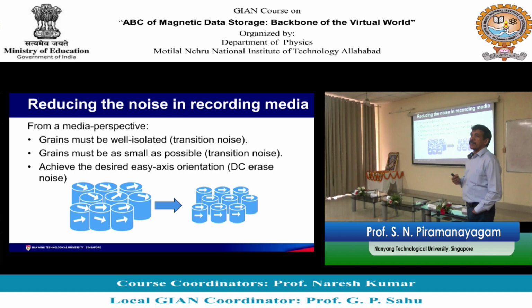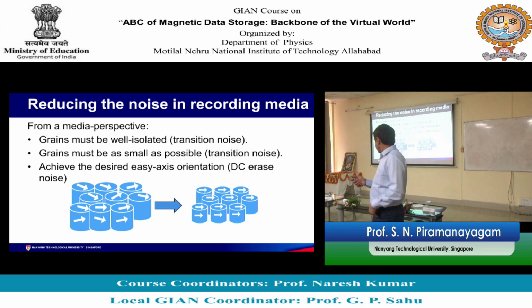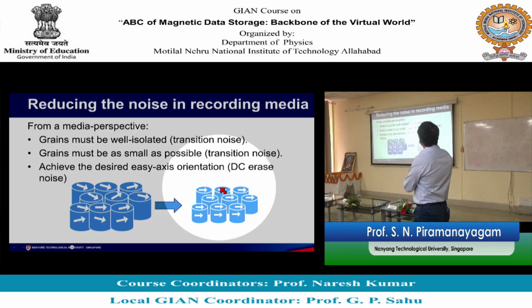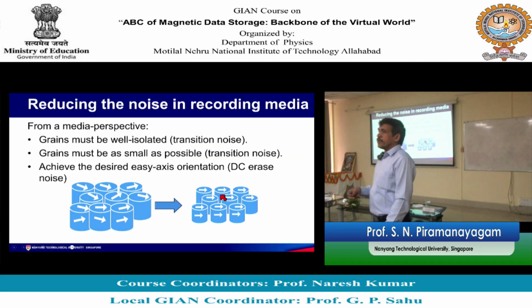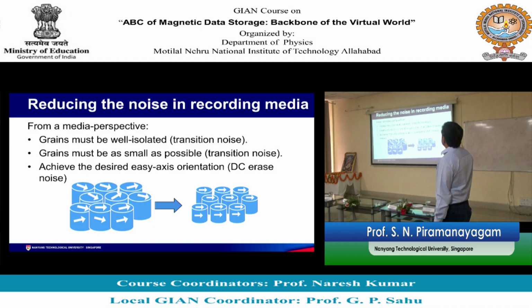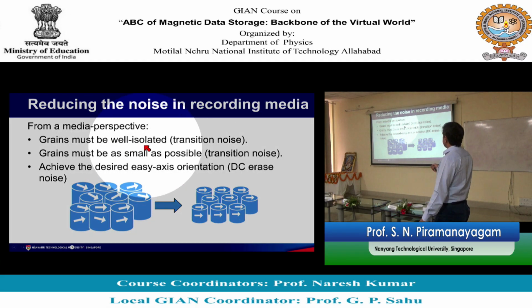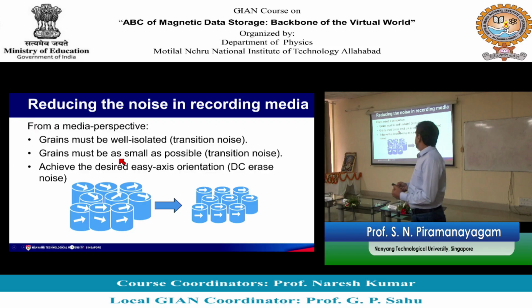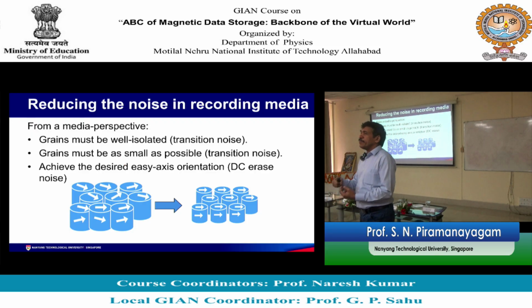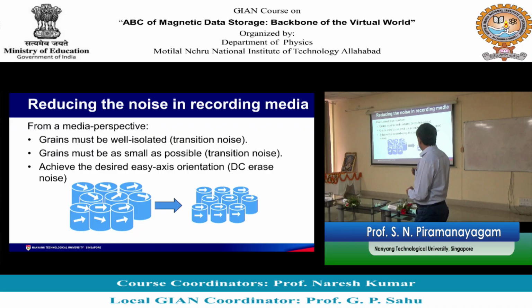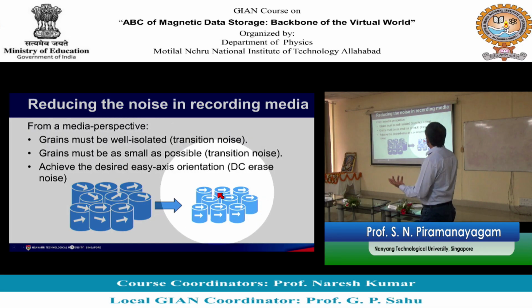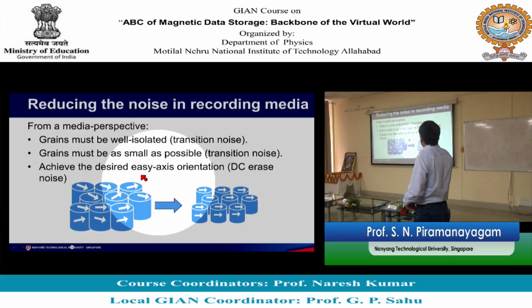I taught you compositional segregation yesterday, which means you have a certain composition within the grain, so the grain is magnetic, and you have another composition at the grain boundary, so the grain boundary is non-magnetic. This way you can isolate the grains from each other. Isolate means it may be physical isolation or magnetic isolation. You can have a non-magnetic material and break the exchange coupling, so the spins cannot be coupled to the spins of the neighboring atoms. That is what we do.